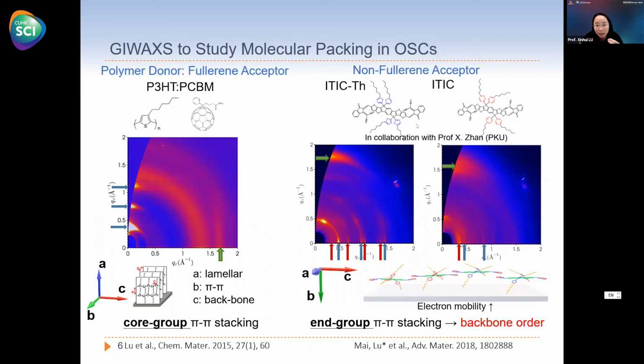And then we studied the packing structure of the milestone ITIC family, in collaboration with the leading scientist, Zhan Xiaowei, who is the inventor of this family. And we find that for this molecule, the pi-pi peak goes to the Qz axis and the lamellar peak goes to the Qr axis. So this means the orientation of the molecular packing rotated 90 degrees to become face-on packing. And on this Qr axis, we observe another set of periodic Bragg peaks, meaning that there's a new structural order in the in-plane direction. So this indicates that these molecules, with this rigid linear backbone, tend to have this end-group pi-pi stacking, which will form a new structural order, backbone order, to facilitate the electron transport in the in-plane direction.